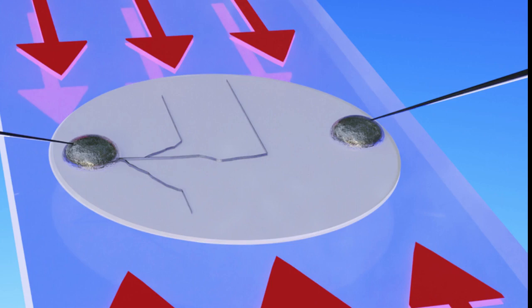In their tests, the researchers used pressure induced by bending the material, which was formed into a beam with a weight at one end. But they say that in practice, there could be many different ways of producing the needed stress. For example, the electrolyte could be made with two layers of material that have different amounts of thermal expansion, so that there is an inherent bending of the material, as is done in some thermostats. Another approach would be to dope the material with atoms that would become embedded in it, distorting it and leaving it in a permanently stressed state. This is the same method used to produce the super hard glass used in the screens of smartphones and tablets.